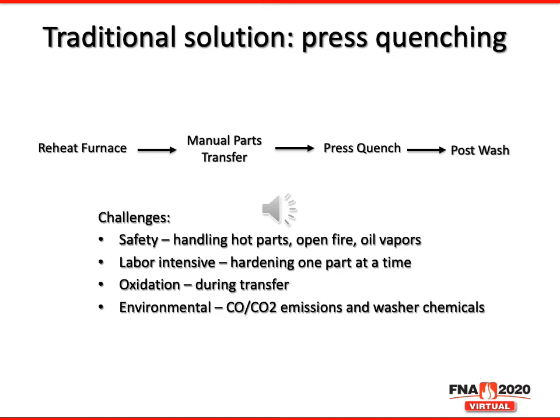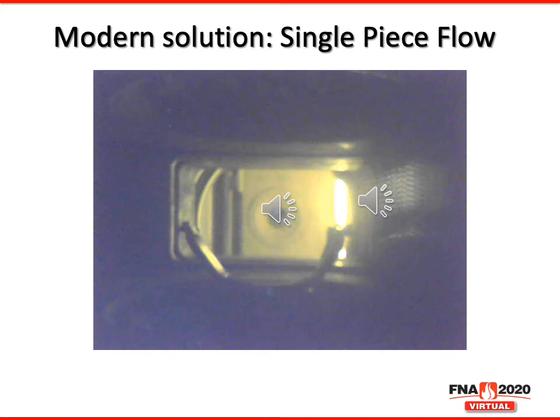So, what alternatives may we have? Instead of using a press quench machine, we can try cooling each part individually in a high pressure gas quench. Okay, why? Well, first, as opposed to regular high pressure gas quenching in batch, this process will allow uniform gas flow around the entire part, unlike the batch process where the neighboring parts will affect the gas flow. Also, rather than just quenching the part statically, it could be rotated to further increase the cooling uniformity. This allows undisturbed flow from all directions, as you will see in this video.